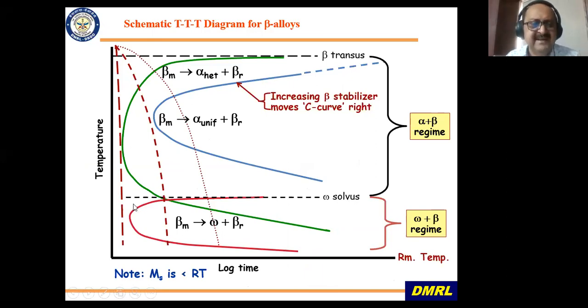Again, you have a TTT diagram. In this case also, you have firstly grain boundary alpha forming, and instead of martensite formation, what you have in beta alloys is the omega solvus. So whether you are quenching it or isothermally aging at low temperatures, lower than let's say 450, 400 degrees centigrade, you are bound to get omega phase, which is embrittling. So you have to be careful in beta alloys, and that is where the problem lies in beta alloys in case of welding and all.